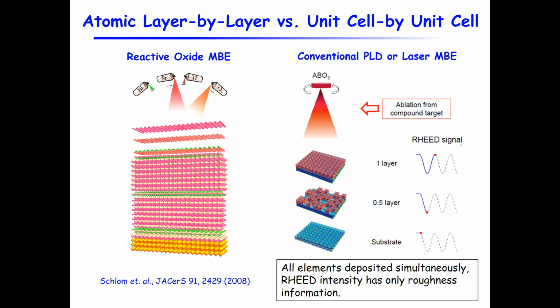So here I show atomic layer by layer growth versus unit cell by unit cell growth. We've seen this from oxide MBE, where you have different sources, and you can open the shutter alternately so that you put down one atomic layer at a time, versus the conventional PLD or laser MBE, where you take a target of the material that you want to grow a film of, and you just shine a laser on it and ablate the material. In this case, all the elements come together. Right? They actually grow unit cell by unit cell. Then you use RHEED intensity.